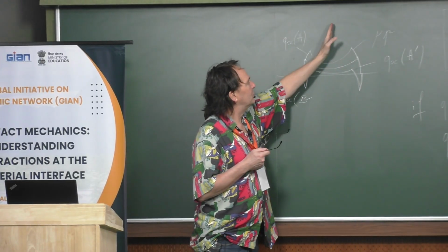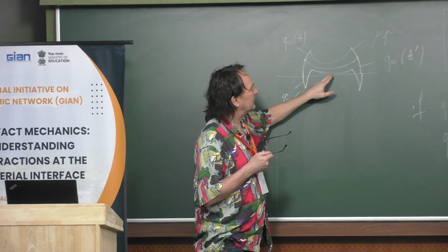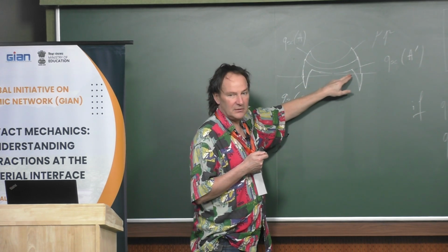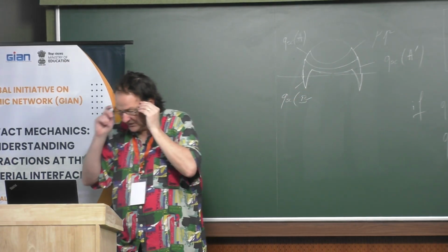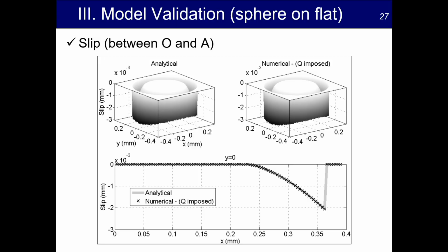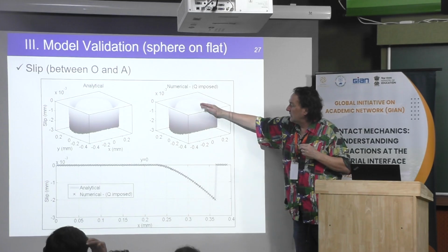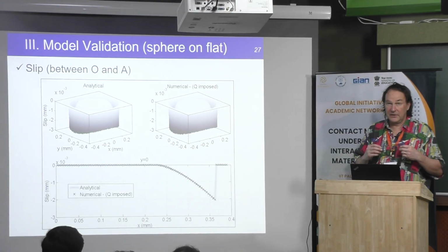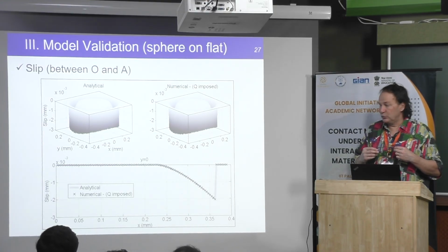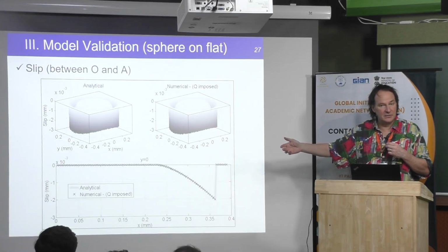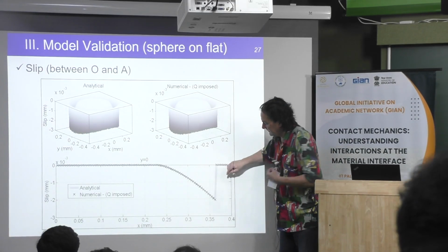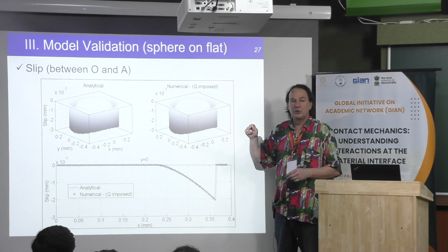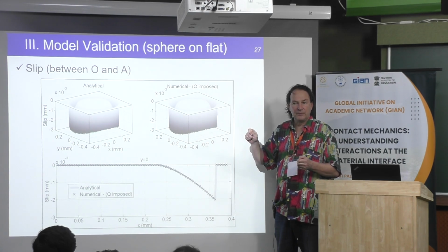Okay. Then if you plot from the center sliding along the x-axis, you will see something which is nil until here that will increase. This is typically this type of curve. Here you have no sliding, and you have sliding at the border. Now, if you want to simulate wear, in fact, the wear will be proportional to the sliding because the energy dissipated depends on the sliding. Then this magnitude multiplied by the shear stress, which is the pressure times the friction coefficient.